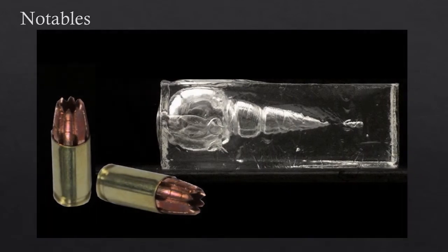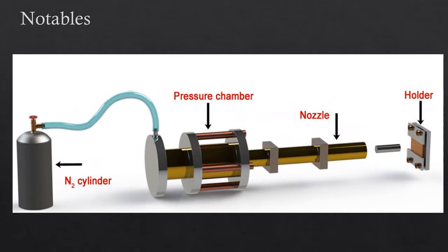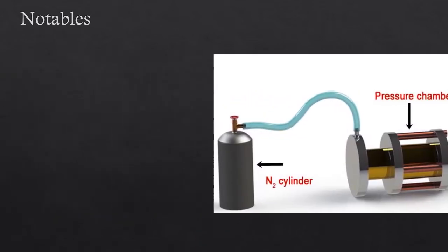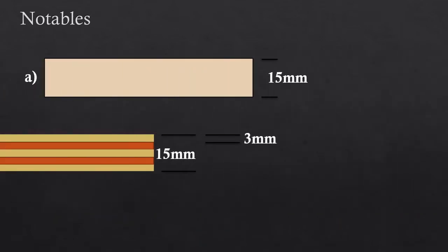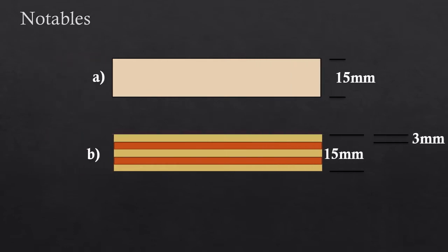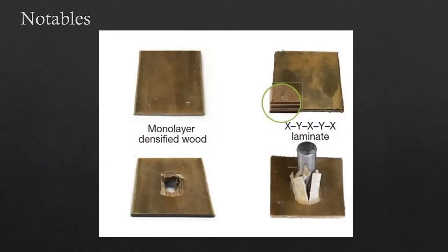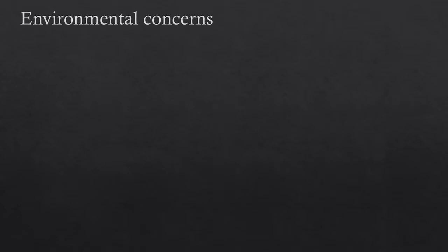And, because who doesn't like to shoot things, the material's resistance to ballistics was tested. This was done to test the feasibility of a lightweight, bulletproof material. To do this, the densified wood was placed in two variations, a single layer and a 5-layer sample with 3 mm thick layers. From the results, it was shown that a single layer sample was unable to stop a projectile, but was 7 times more resistant than natural wood. The 5-layer sample showed that a projectile will penetrate the sample, but it will be trapped in the middle layers and won't completely exit the sample.